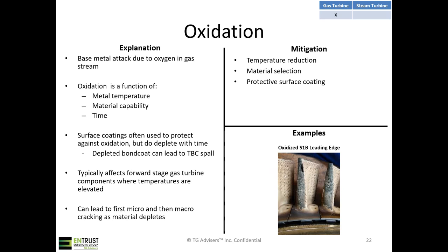There are different types of surface coatings that can be used to protect against oxidation, but they do deplete in time. For example, if you had a bond coat underneath the TBC, your bond coat would essentially be protecting the base material from oxidation, but it will deplete over time. And when your bond coat depletes, a lot of times the TBC lets go because the bond coat is not good anymore. And from there, you'll see elevated temperatures. We call those post-spall temperatures, where oxidation will begin to occur rapidly.